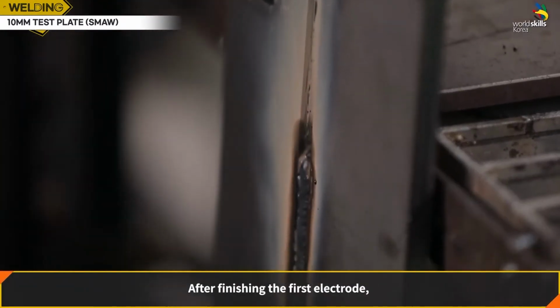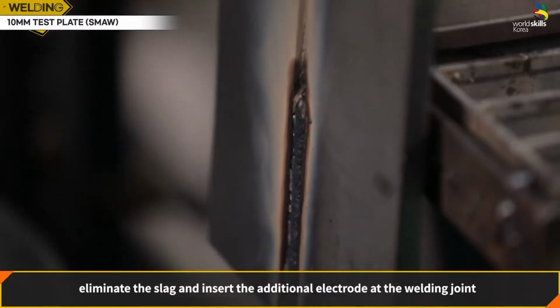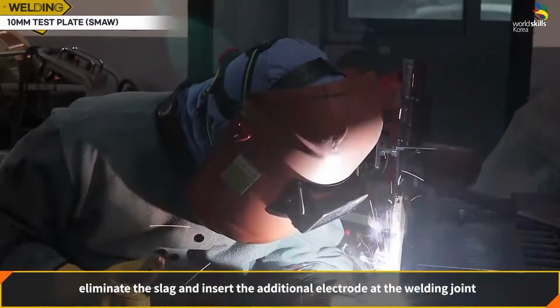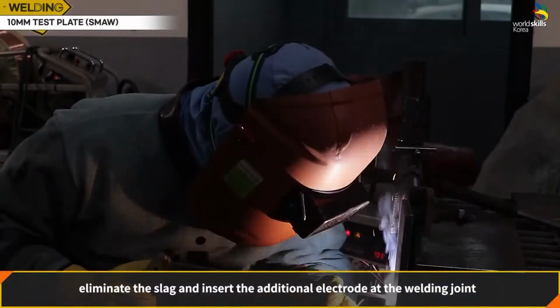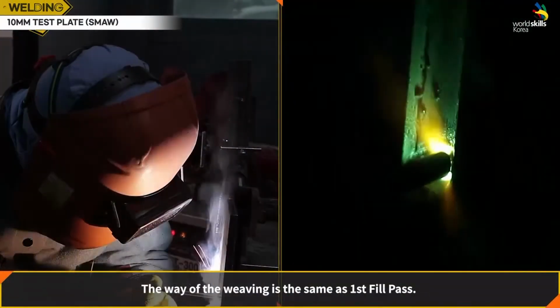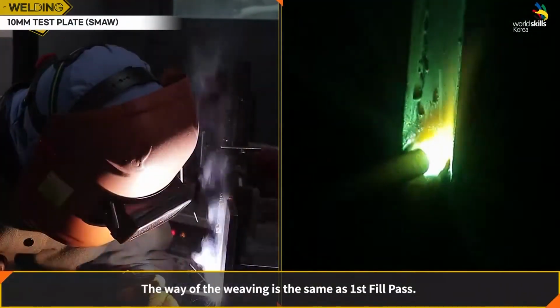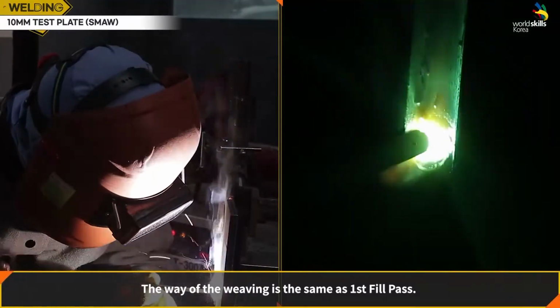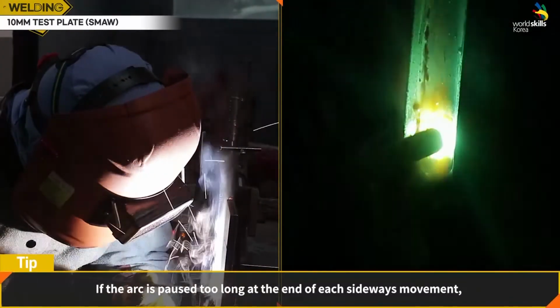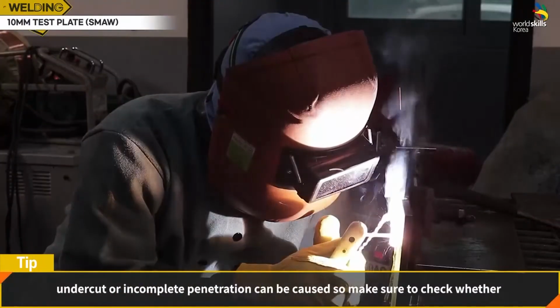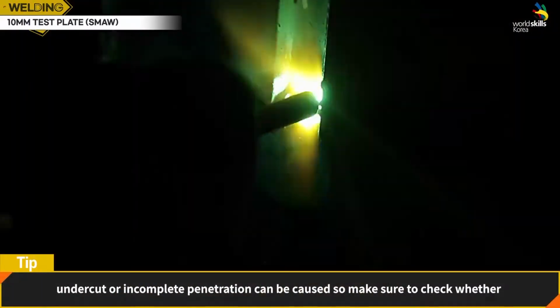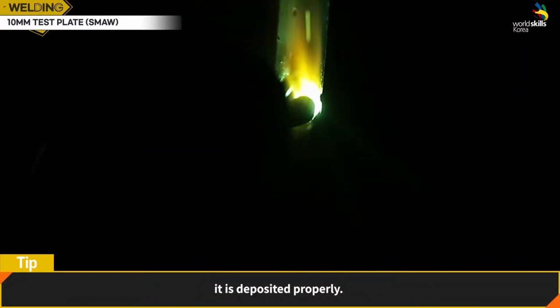After finishing the first electrode, eliminate the slag and insert the additional electrode at the welding joint. The way of weaving is the same as the first fill pass. Be careful because staying at both ends of the V-groove for too long may cause undercuts or improper penetration.